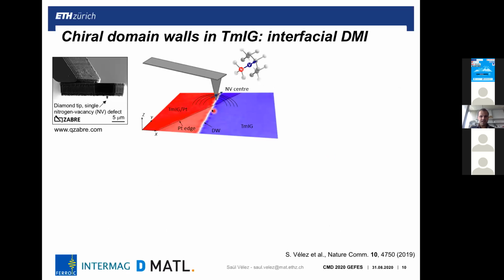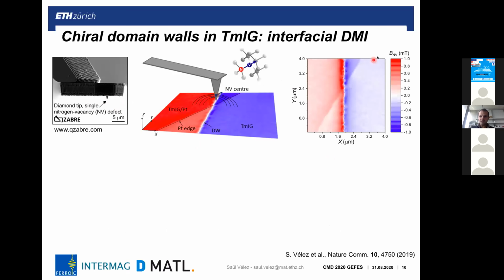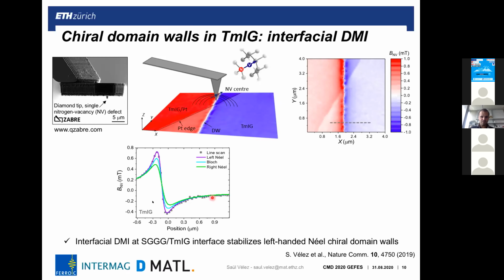So we now measure the chirality of these domain walls by using a nitrogen vacancy magnetometer. Basically, we have a defect placed at the apex of a diamond tip, and we measure the stray field of a domain wall, in a part that is partially covered with platinum and a part that is not covered with platinum. So this is the stray field map that we record, and now we fit the stray field to the expected domain walls, the different domain walls that we could have: the Bloch wall, which would be expected for a system in which we don't have a Dzyaloshinskii-Moriya interaction, and the left and right Néel domain walls where we do have Dzyaloshinskii-Moriya interaction.